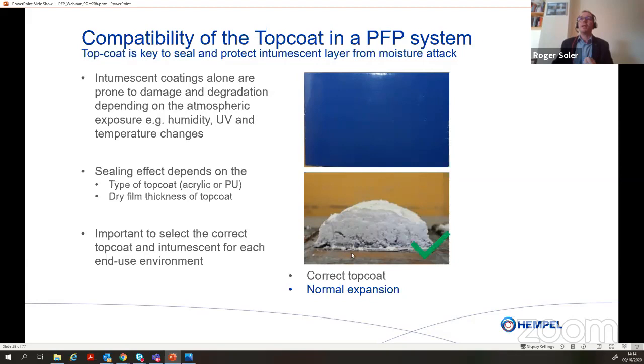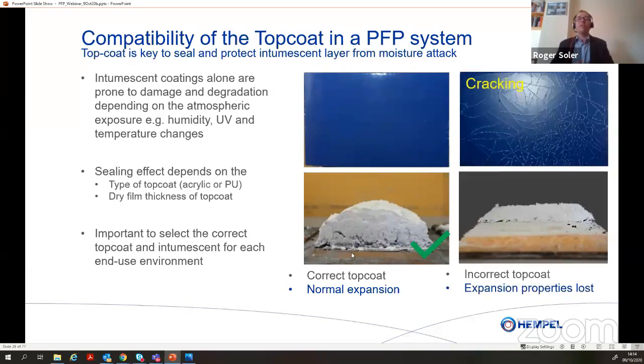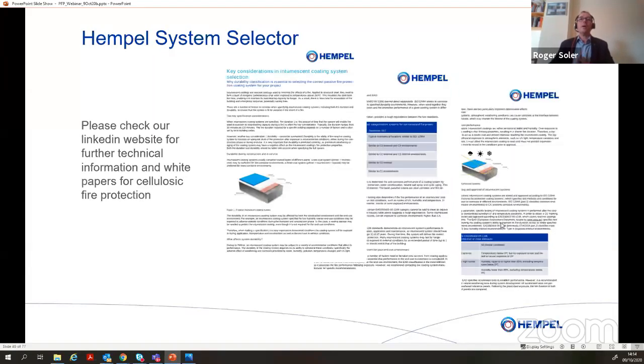But some systems might not be compatible once they've been exposed to this aging. So there might be cracking, for instance. And through this cracking, the humidity could penetrate to the intumescent layer, and depending on the type of intumescent paint used, it could be not resistant to that, or at least reduce the intumescence level, so the expansion properties would be lost. So again, this would be a failure to protect the steel structure.